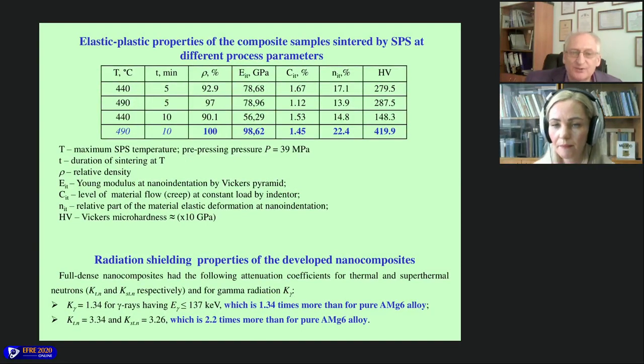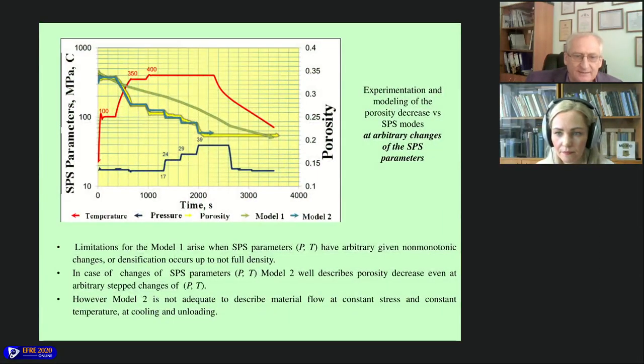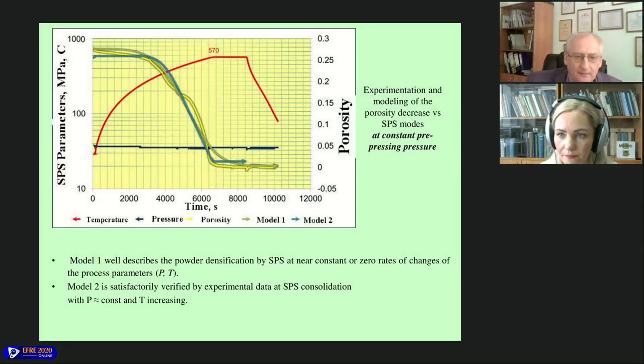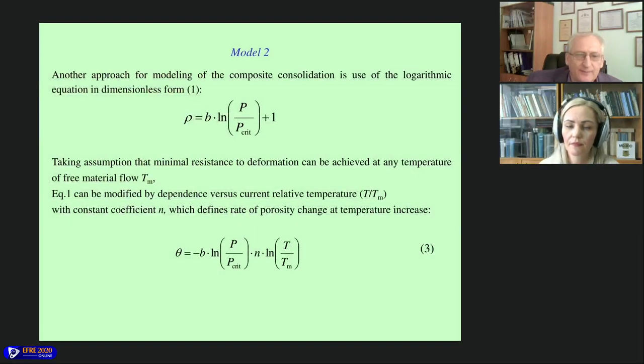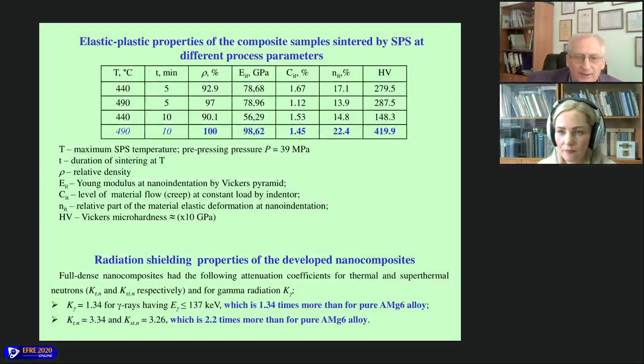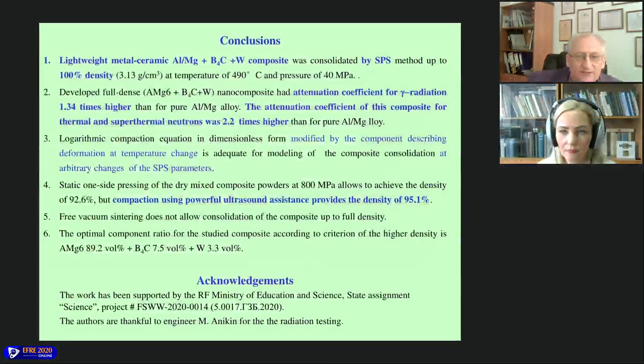Without mechanical activation, by SPS processing, we obtain full dense composite. But if we used just pressing using the powerful ultrasound assistance, we obtained the composite having just 95% of relative density. This conclusion: mechanical activated powder by the powerful ultrasound assistance with following sintering could achieve just 95% of density, but spark plasma sintering without mechanical activation allowed us to achieve full dense composite.